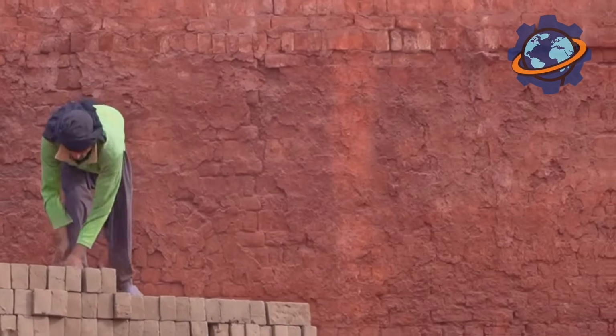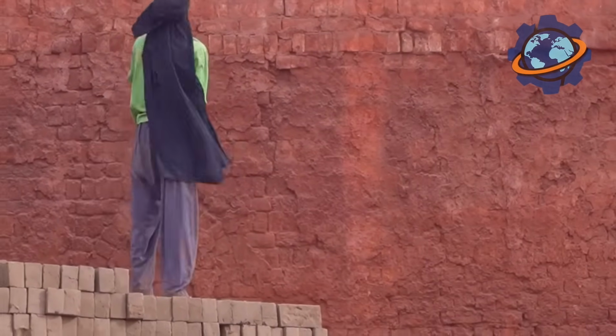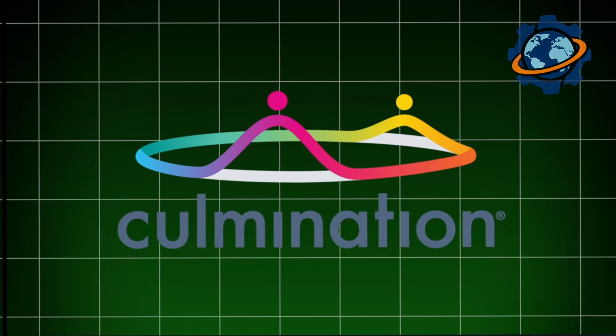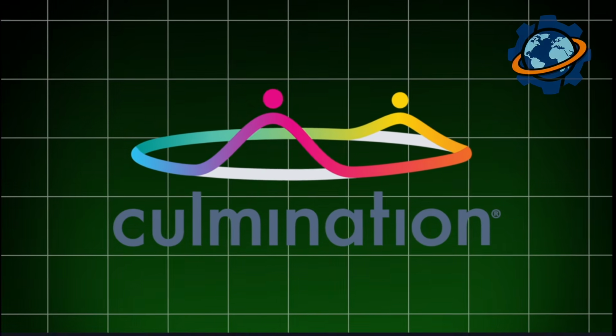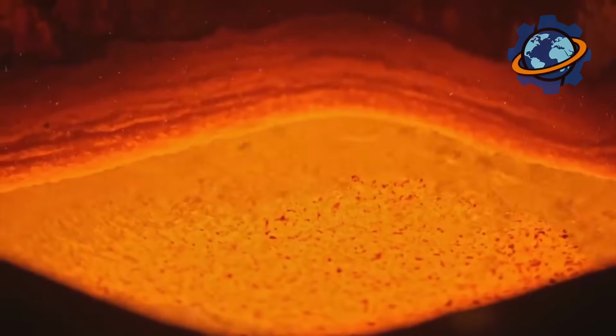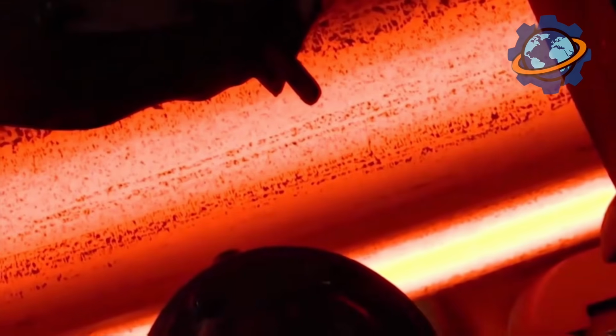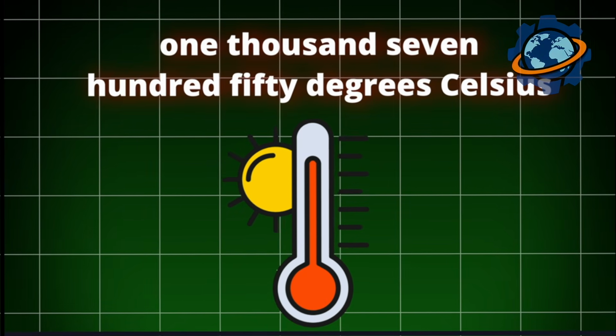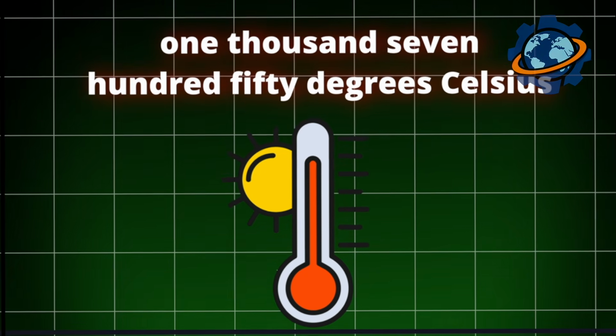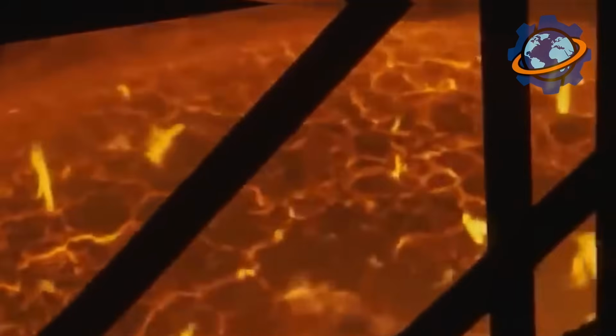When all the physically bound water is removed, the culmination of the entire production cycle begins: firing. The brick enters the fiery tunnel of the kiln, where a true rebirth awaits it. Slowly moving through different zones of the kiln, it is gradually heated to peak temperatures, which for chamot brick are 1,400 degrees Celsius, and for high alumina types can exceed 1,750 degrees Celsius. This is not just drying, it is a deep metamorphosis.